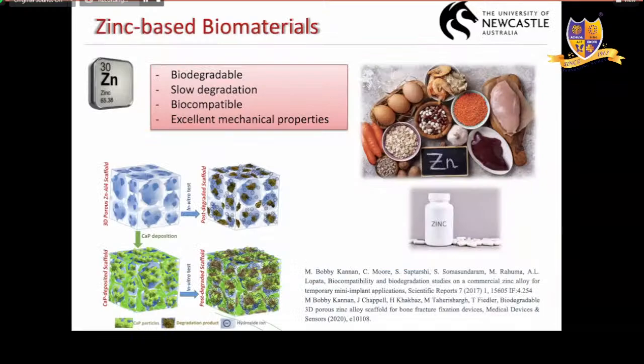Quickly, I want to talk about the other research I'm doing in my lab. One is zinc-based materials, which is similar to magnesium. We were the first to develop a porous zinc material for biodegradable implant applications. It has all these beautiful properties, and in fact the degradation rate is lower, but it has other complications, toxicity complications, which, if you're interested, you can read in these publications, where we have the details.